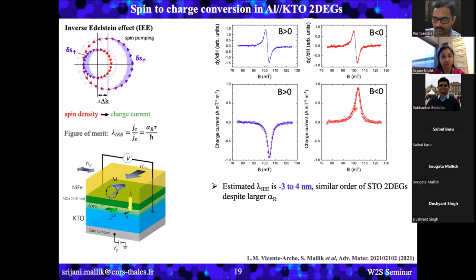So it's really nice. And then we estimated the lambda for this. We got it to be 3 to 4 nanometer. That is a similar order of STO 2DEGs. So we know that we have really high Rashba spin orbit coupling in our samples, but finally we are not gaining in the lambda. So here I would like to bring to your notice that the lambda depends not only on alpha, but also on tau.